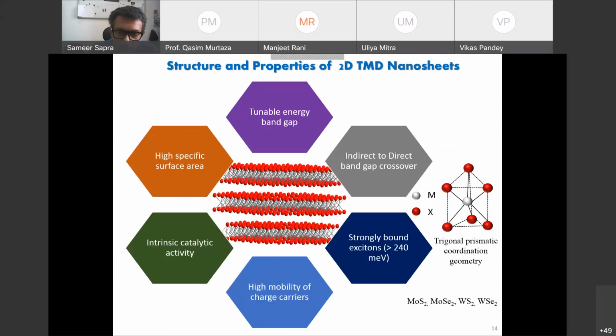So to sum up, you have the structure and properties of these 2D transition metal dichalcogenide nanosheets. These are layered structures, and all these layers can be exfoliated. As I showed you in the first picture of nanomaterials, I can have different colors, which essentially means that I have a tunable energy band gap. The same thing is true with these materials. I'll dwell a bit more on that. And I've already told you there's a direct to indirect band gap crossover. We'll mostly work with one-monolayer sheets, so mostly with the direct band gap materials.